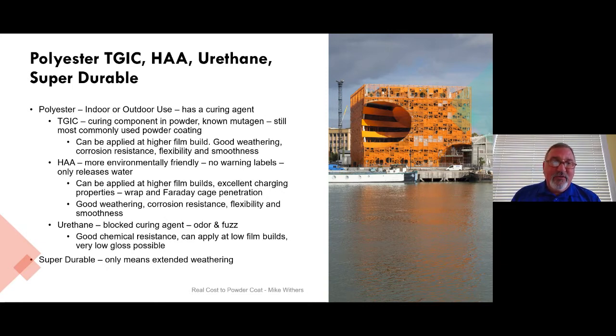Now, urethanes, they also can go indoor or outdoor, but they are much smoother. They have a blocked curing agent, so there is some fuzz. If you notice around the entrance and the exit of the oven, you'll see some brown fuzz. That's the covering on the curing agent that releases at the right temperature. There can be some odor with these. You will notice the smell in the air as the product is baking. But the very low gloss, now, we talked earlier about epoxies and they can have the full range of gloss. Urethanes have that full range of gloss as well. So if you're looking for a product that polyester TGICs and polyester HAAs cannot achieve, a urethane may be an opportunity for you there.